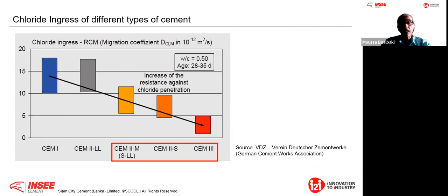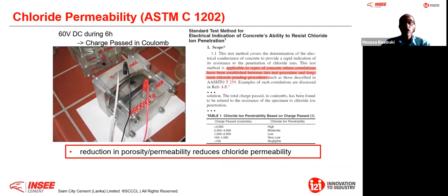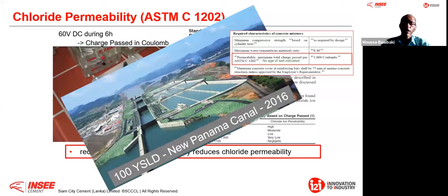That is really why, if you take a project, they use this test method. They have put what we call durability indicators on chloride penetrability. This is the ASTM test. When you are below 2000 coulomb, you are what we categorize as low in terms of chloride ion penetrability. A project like, for example, the new Panama Canal with a 100-year service life design, where the requirement is 1000 coulomb, water-cement ratio 0.4, with Portland composite cement.